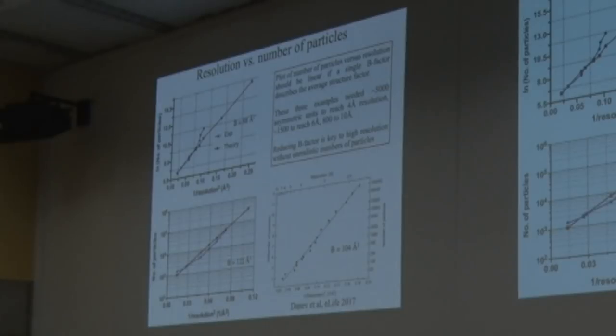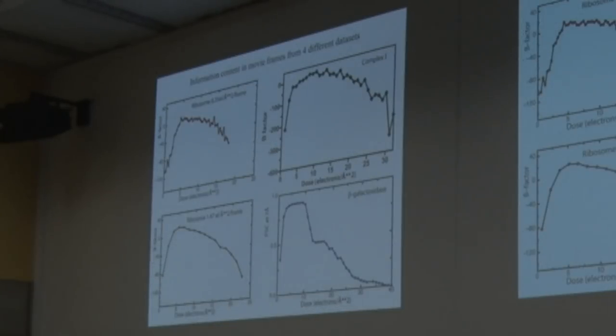Okay, so another plot that we like, I'm only going to show you two. This is the next plot: information content in the movie frames. Because you press the button and you get a movie now, and then you try to do the alignment. If you could perfectly align for any blurring or image motion, then every frame would be perfect, and actually, the first frame would be the best one. But actually, the first frame is almost the worst. And then it gets a bit better. And then between about 5 and 10 electrons per square angstrom, the middle part of the movie, you get good data with a low B factor. And then the map you get is, of course, a combination of all of them. But all of these, two ribosome data sets, mitochondrial Complex I, beta-galactosidase, all show the same features.